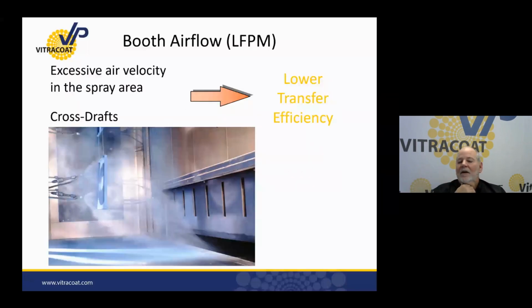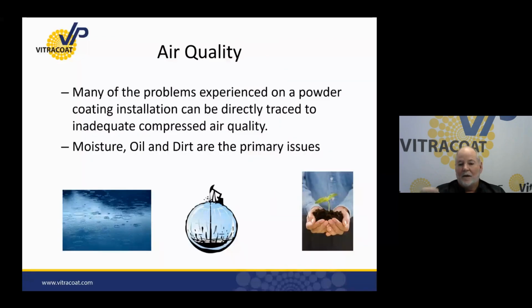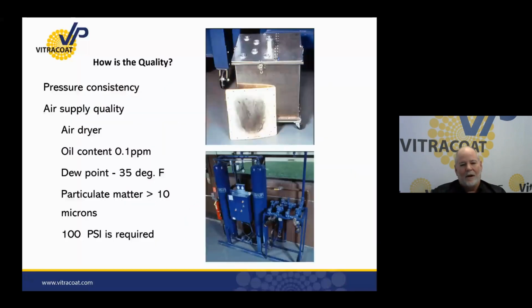Velocity of air. You can have a booth that's perfectly designed at 110 linear feet per minute of air movement along all openings. And then you add air conditioning venting or fans on a hot day that have cross drafts, and it will change it dramatically. Final filters getting plugged will change it dramatically. Always look at linear feet per minute. Check it. Mark it. Collect the data. Look at air quality, because the air quality is critical to a powder coating operation.